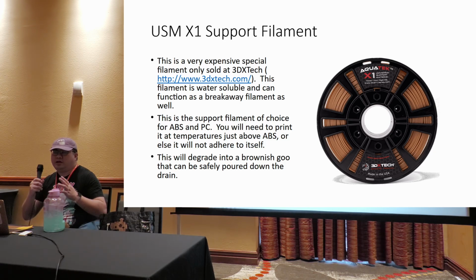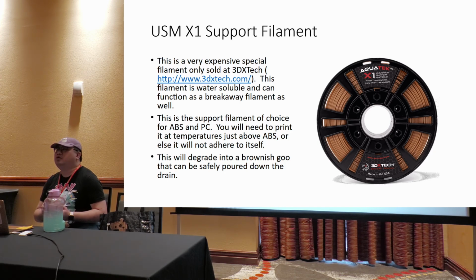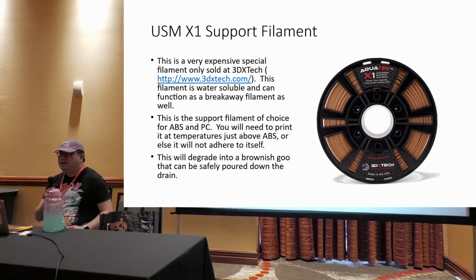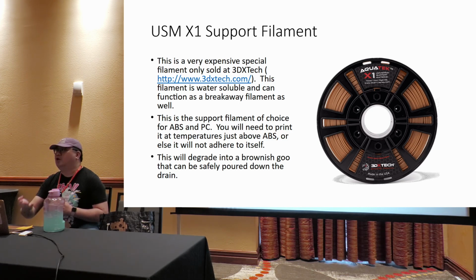You will have to print it a little bit hotter than ABS, but otherwise it will work for ABS just fine. But those of you who have done this for a very long time, you may recall the old way to do ABS support filaments was this really weird HIPS, which basically collapses after you dip it into a solvent. This uses water. And personally, I am not a fan of having special solvents just to do ABS. But this works for ABS, polycarbonate, polypropylene, and anything in that particular temperature range.